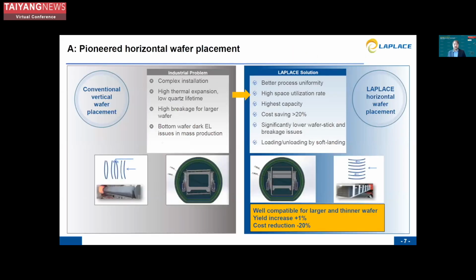So let's quickly talk about this horizontal wafer placement. Here, as most of you know, the standard is that the wafers are vertically placed. We can reach a much better process uniformity and especially also use trays much more efficiently and therefore increase the capacity by placing the wafers horizontally.